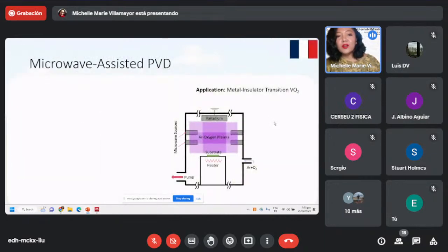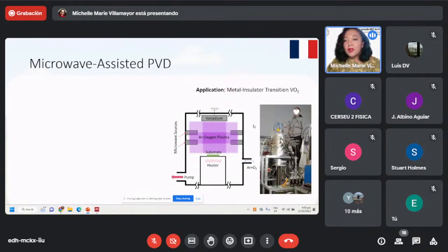Now, there's another way of creating plasma, and this is called microwave-assisted physical vapor deposition. This time, we use microwave sources on the side, and then this ignited argon-oxygen plasma sputters out the vanadium, and the sputtered vanadium reacts with oxygen to deposit vanadium oxide or vanadium dioxide onto the substrate. It's very important to heat up the substrate if you want to deposit VO2, otherwise we end up with different oxidation of vanadium. And for this size, it's almost half the size of a person.